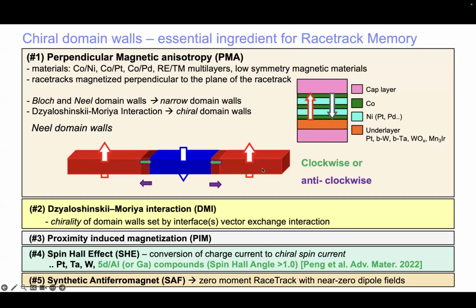And the reason why they're chiral is because of this platinum underlayer. The same layer in which we generate spin currents through spin Hall effects, the interface between that layer and the magnetic layer leads to a broken symmetry and leads to something called a Dzyaloshinskii-Moriya interaction, which means the moments at the interface want to be perpendicular to one another in a chiral fashion. And it's common to many heavy metals.